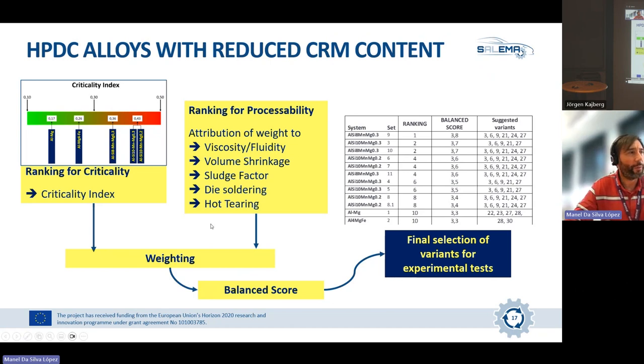Then we also predict these 5 factors: the viscosity, shrinkage, sludge factor, die-soldering, and hot tearing. We weighted one third for the criticality and two thirds for the castability. So the processability is more important, being able to process the alloy, than whether it's critical or not. We give a score to each of the over 70 alloy variants that we test. From that we select 2 families: aluminum silicon manganese magnesium and aluminum magnesium families.